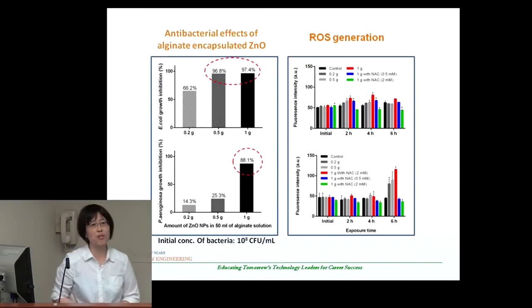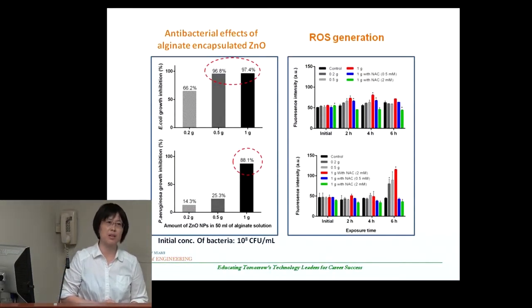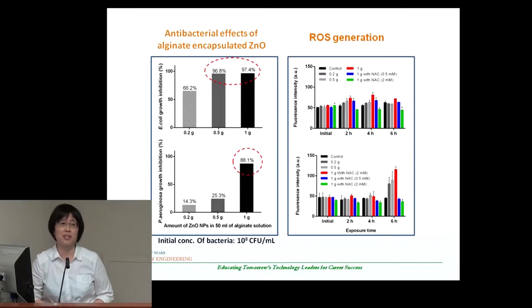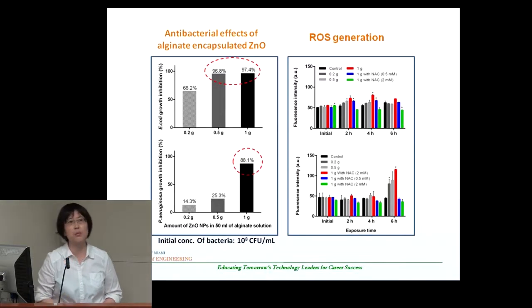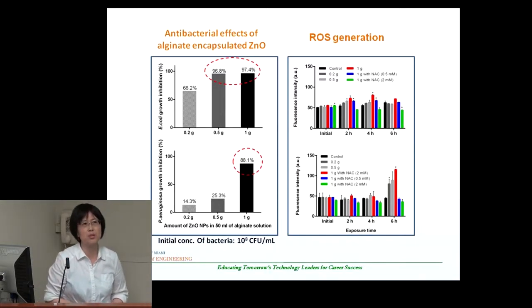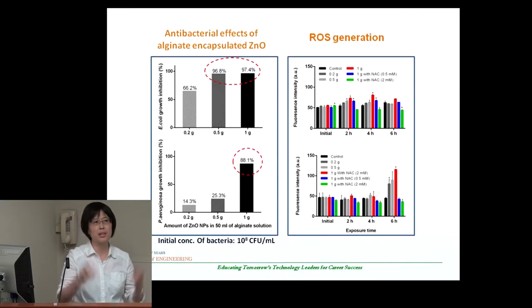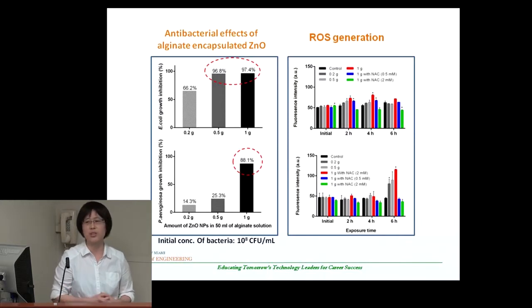Now people are confused about whether E. coli is a deadly bacteria, but there are many different types of bacteria present in water. So the E. coli that we used was DH5 alpha type, which is one of the antibiotic resistant bacteria, and also Pseudomonas aeruginosa. This is one of the multi-drug resistant bacteria. So we found very interesting, significant removal with only a small amount of zinc oxide encapsulated in the alginate bead. The alginate is an environmentally friendly, biodegradable material.